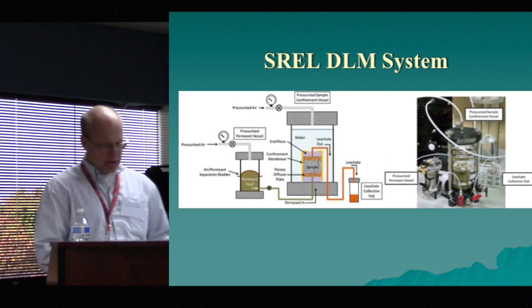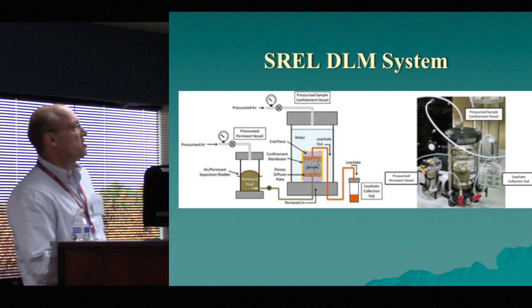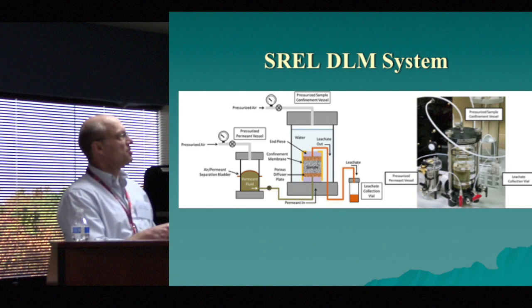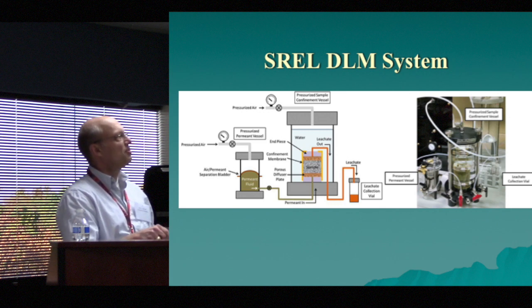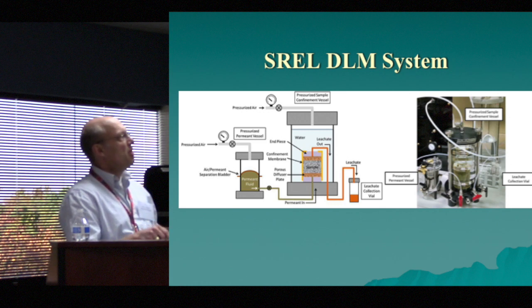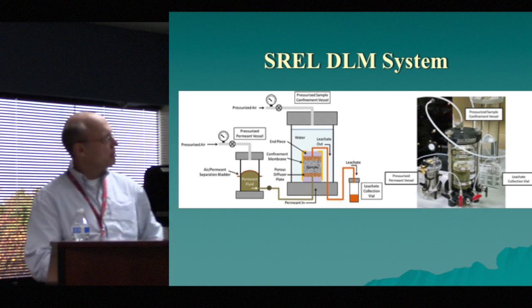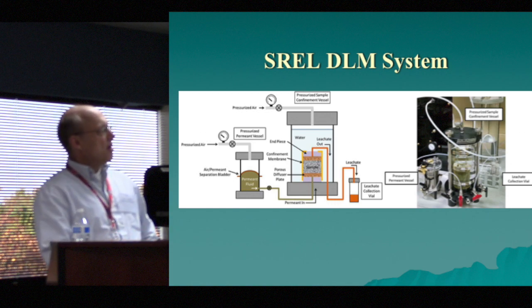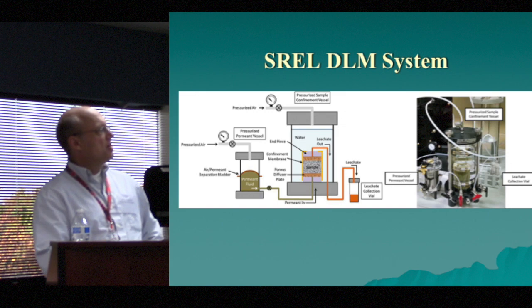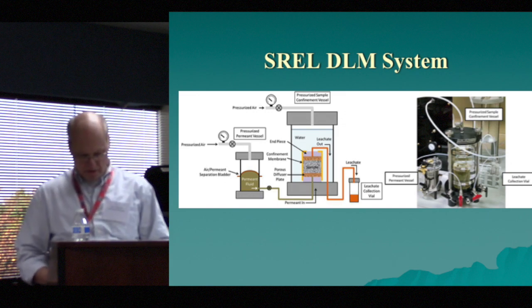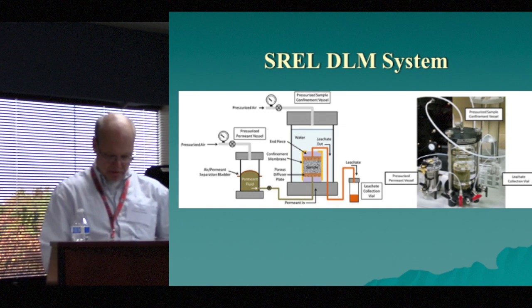So this is a better diagram of the entire system, and some of the tubing actually disappeared in this version. I don't know what happened. What you have here is your confining pressure on your sample in the chamber. You're then applying a driving pressure for leaching, and you're collecting the sample at the effluent here. And that is an actual picture of the system as it exists.